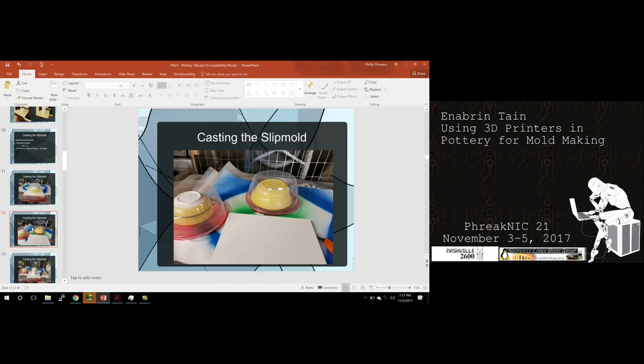Have you discovered a lovable detail where a 3D-printed object had a lot of detail that couldn't be captured in the plaster? The limit is actually going to be that you're dipping it in wax, not that the plaster can't take it. I've cast stuff where I could actually see the ridges from the 3D printer because I was using a 0.3mm layer height and just didn't have the wax that thick. The plaster can pick up all the detail.